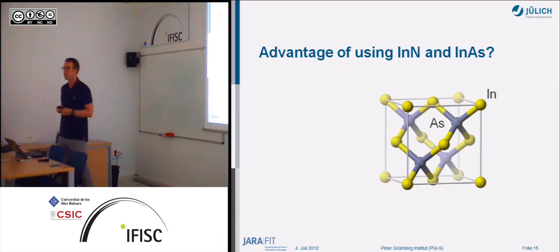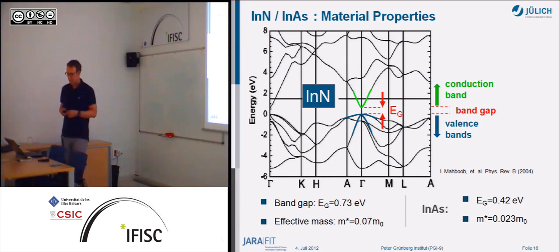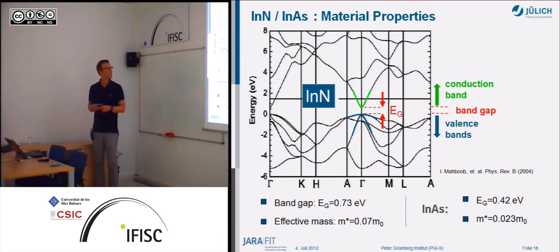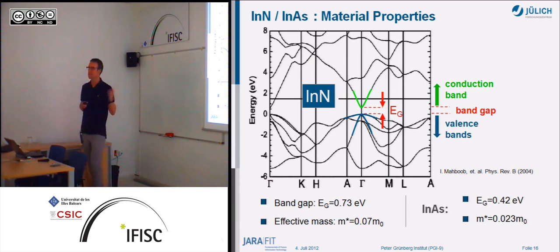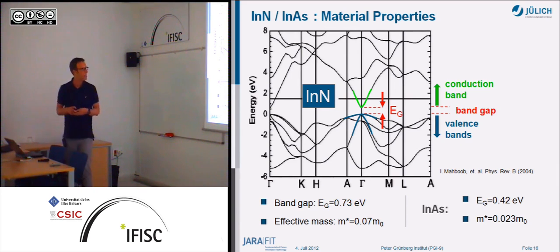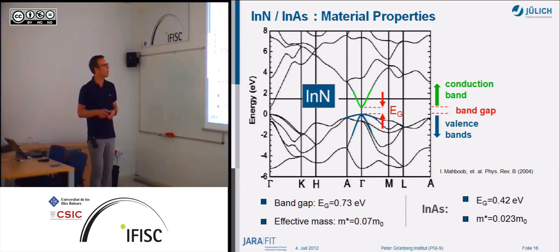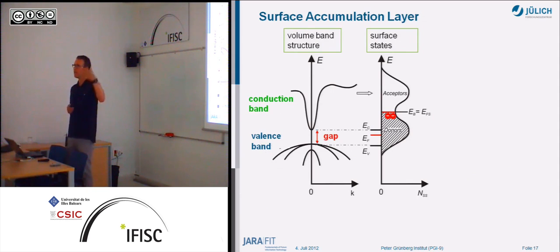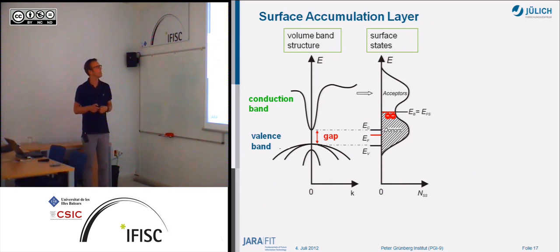So what is the advantage of using indium arsenide or indium nitride for semiconductor nanowires? The reason is that in these semiconductors, the band structure is in that way that we have a small band gap. Here you have the valence band, you have the conduction band here, you have a small band gap. For indium nitride, it's around 0.7, for indium arsenide, 0.4. And the interesting thing is that the conduction band goes deeply down almost to the valence band here. But you have a small density of states here. And this is the reason why you have a certain surface configuration at the end. And that's shown here.